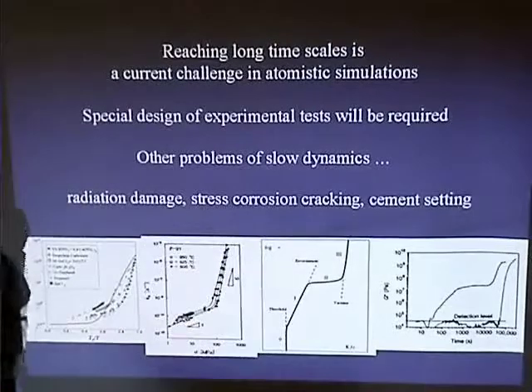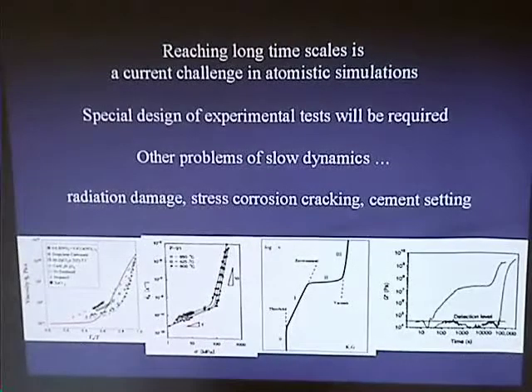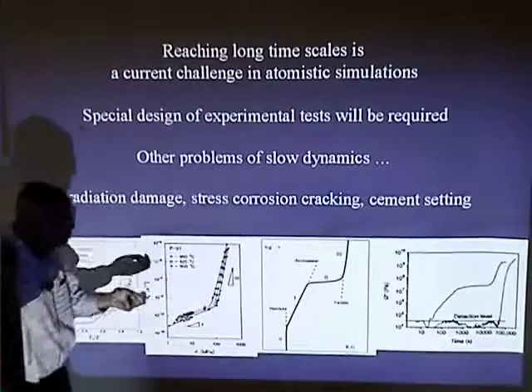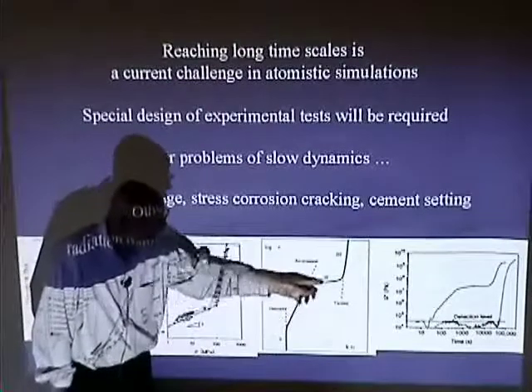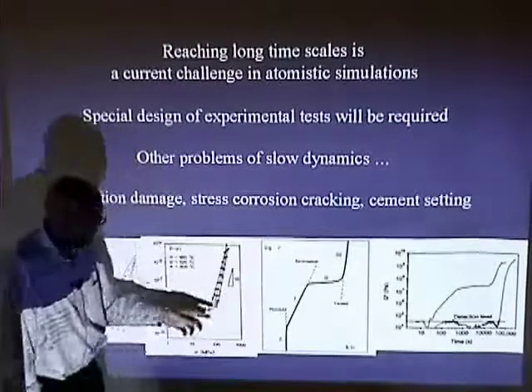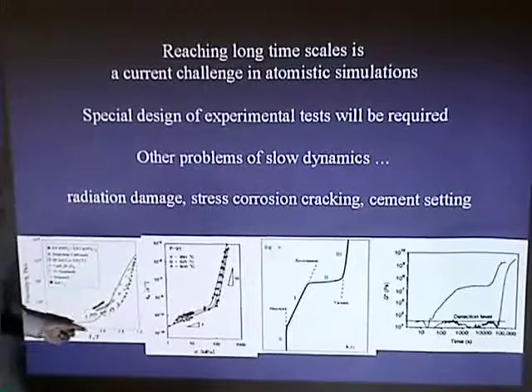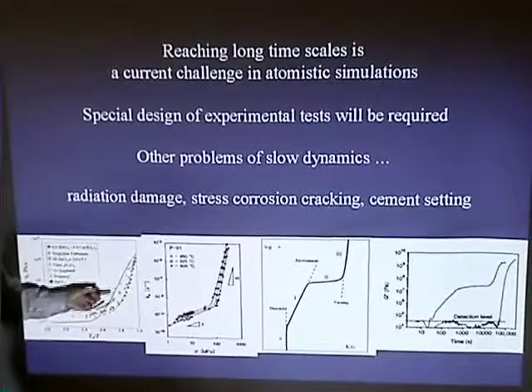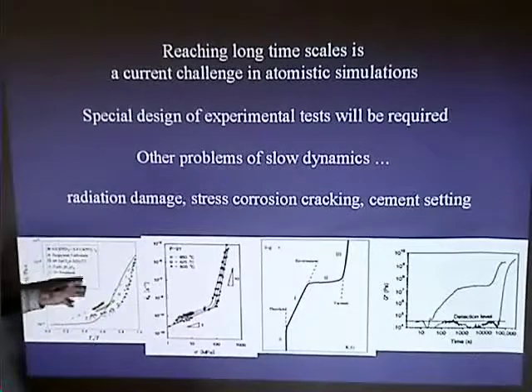Corrosion phenomena is well known to have these kind of slow crack growth. In stress corrosion cracking, you have 3 stages: you have corrosion, then a plateau, and then another rise. And so here's our plateau and a rise in viscosity. We've already talked about that.